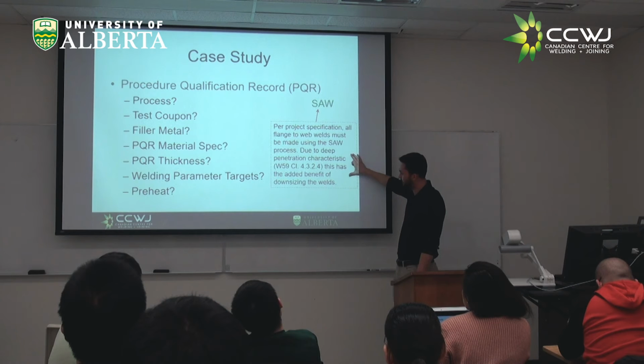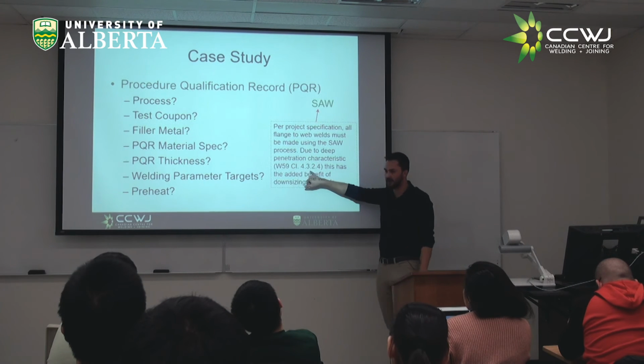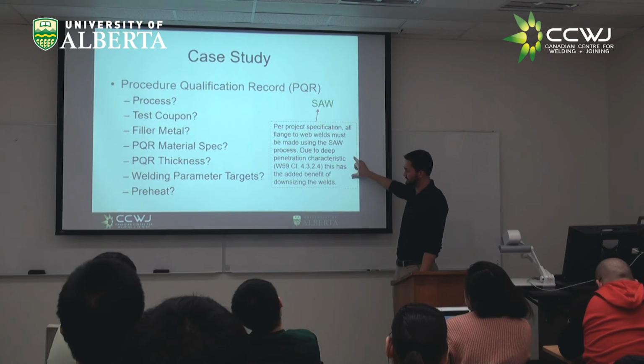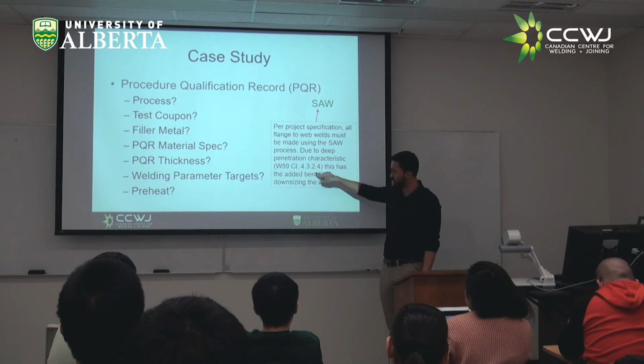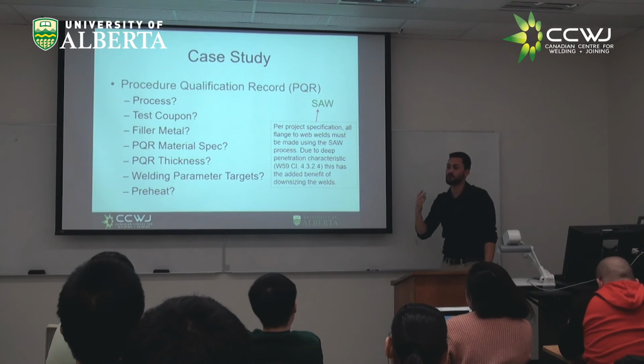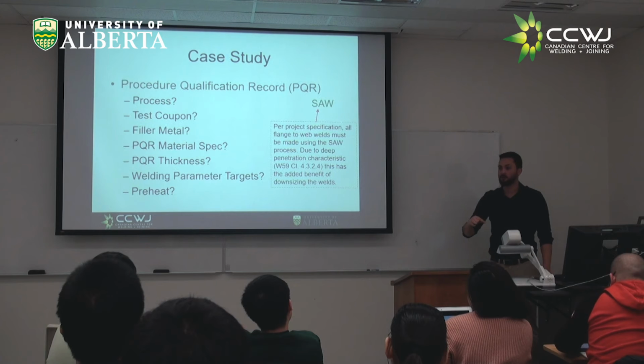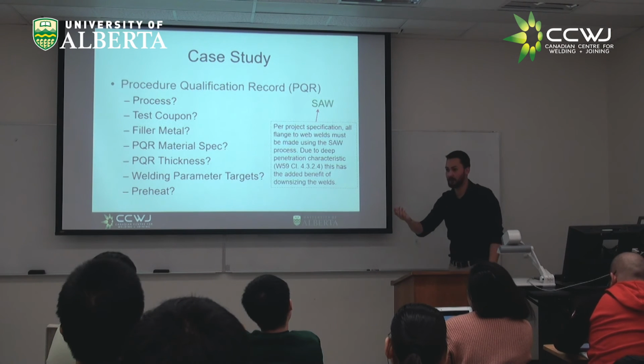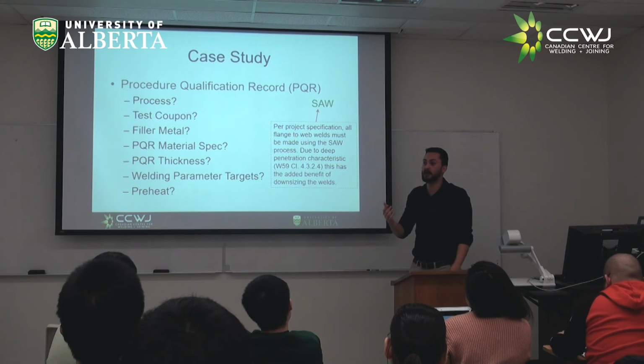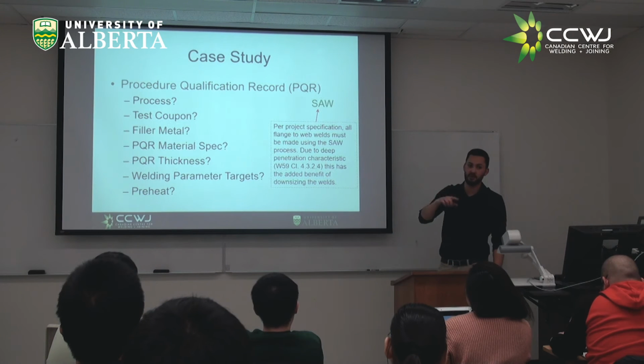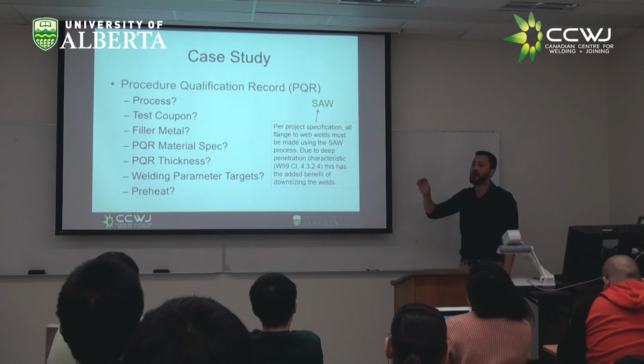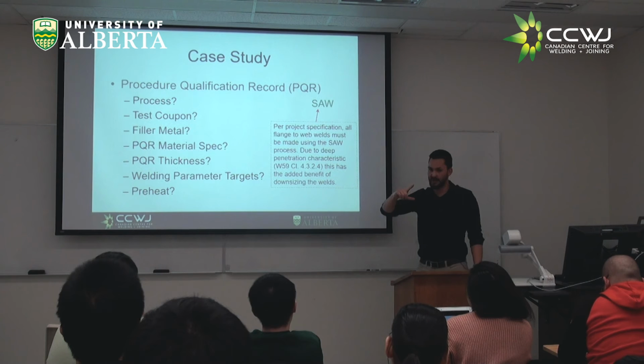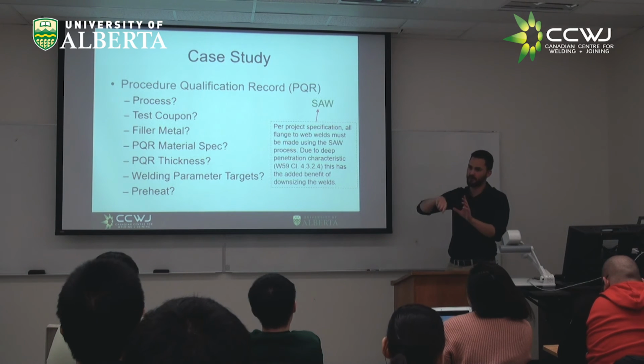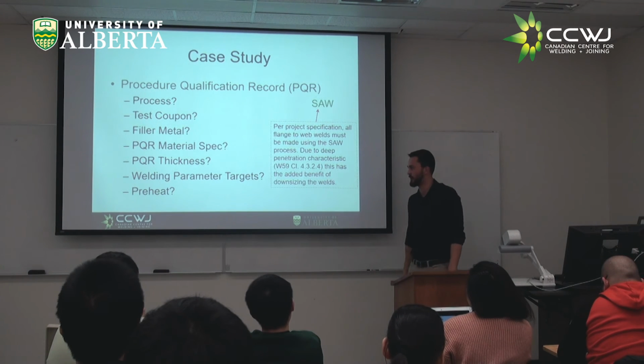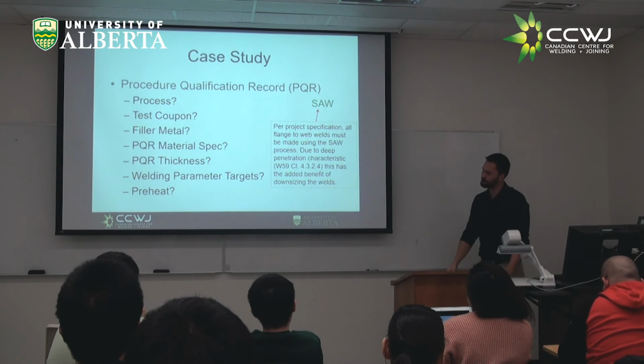And it's consistent to the point where actually, there's a clause within W59, the construction code, that says that when you weld with sub-arc, you get to add essentially 1 weld size to your weld. So if it makes you feel better about the 8 mm fillet weld, it's actually a 10 mm fillet weld. So they consider, because of how deep the penetration characteristic is, that you're actually getting a 10 mm weld, even though all that's on the outside is 8 mm, right? Because you're penetrating down, and those 2 millimeters in the corner there are adding to the strength of that weld.